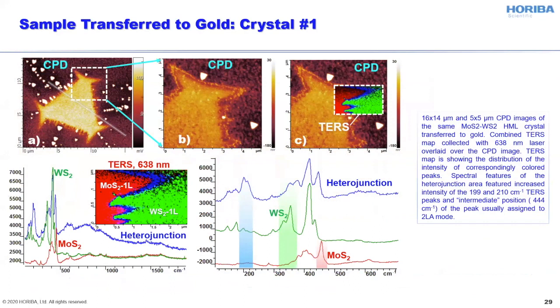So first we took a tip-enhanced Raman scattering map with a 638 nanometer laser, and we got a quite nice high resolution image with several important features in it. So first of all, we clearly see signatures of molybdenum disulfide and tungsten disulfide far away from the junction area.